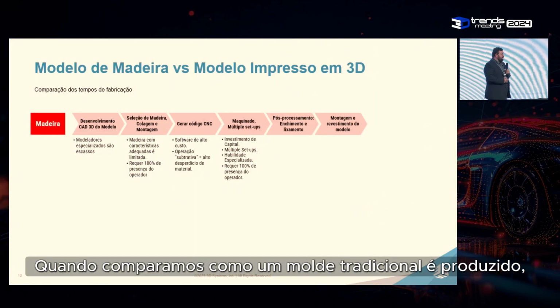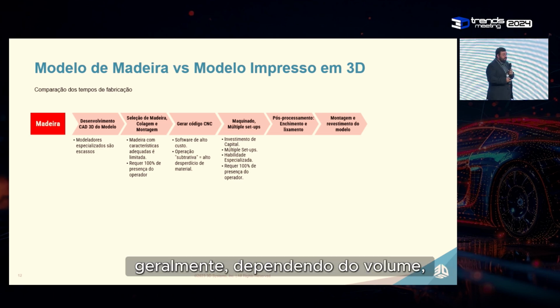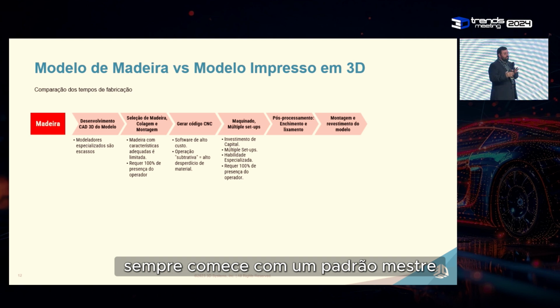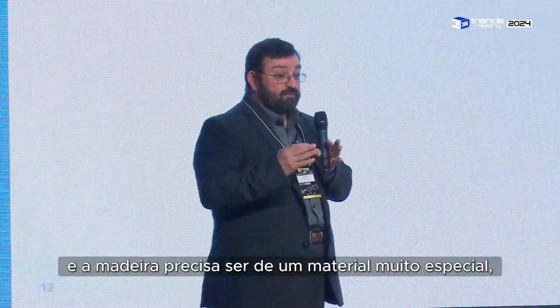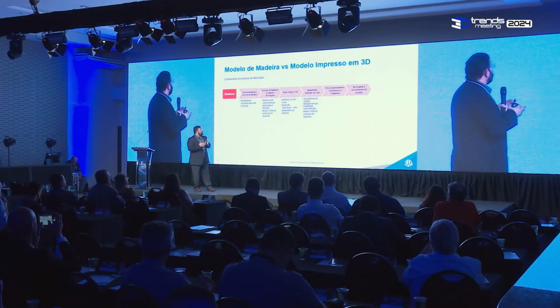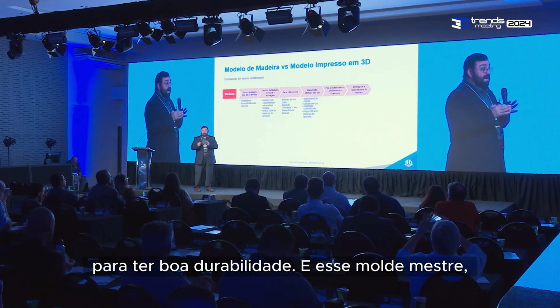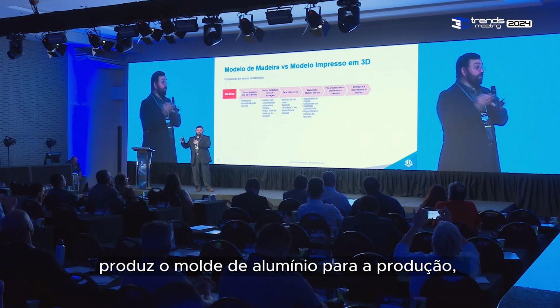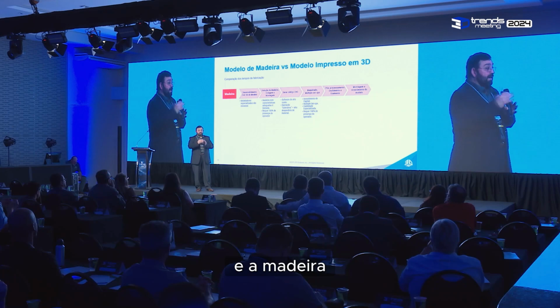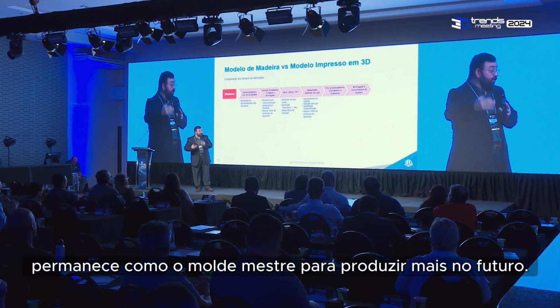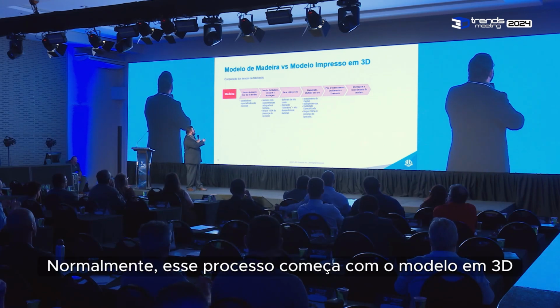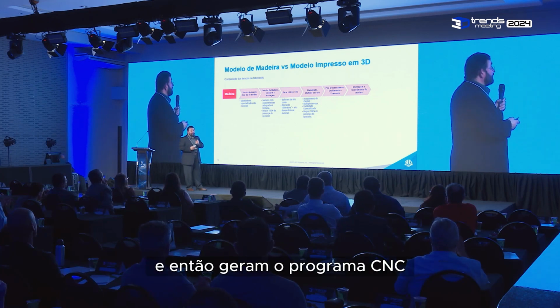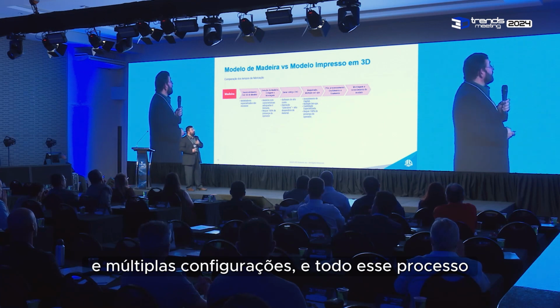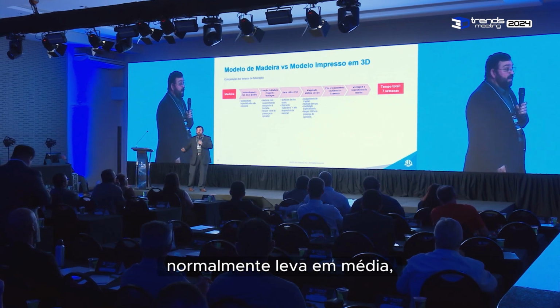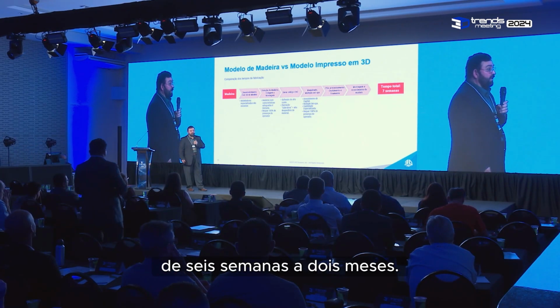When we compare how a traditional mold is produced, depending on the volume, it always starts with a master pattern. The master pattern is done with wood. And the wood needs to be a very special material, like mahogany, to have good durability. If the volume is going to be big, that master produces the aluminum pattern for production, and the wood remains as the master to produce more in the future. Usually this process starts with the model in 3D, then generates the CNC programming and multiple setups, and all this time, on average, parts take between 6 weeks to 2 months.